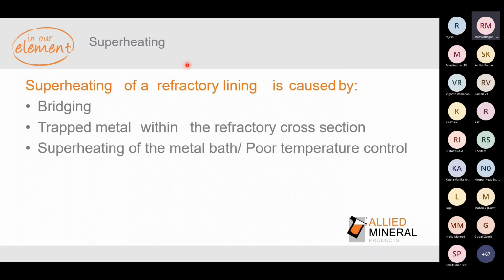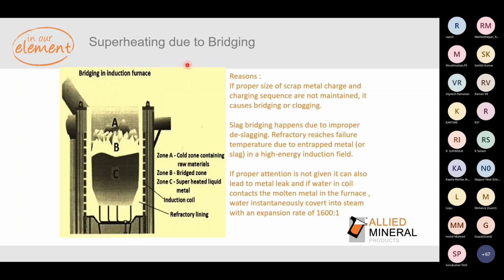Coming to superheating. Superheating can be because of bridging or trapped metal within the refractory cross section, or superheating of the metal bath because of poor temperature control. So as I said before, if improper charge or scrap is done during the charging practice, the huge scrap will not allow the smaller scraps to get in, and there'll be a lot of hangups.